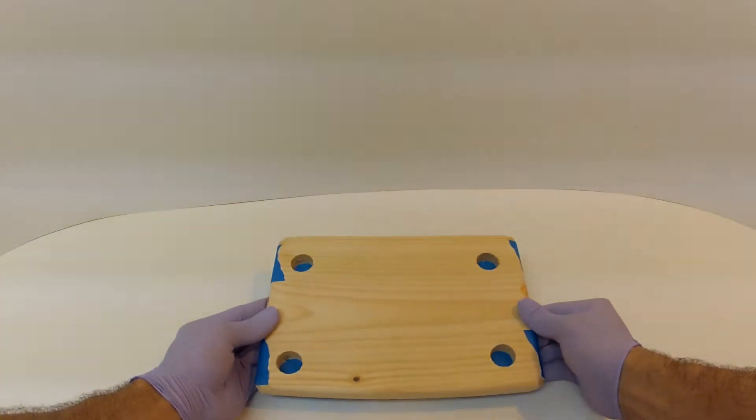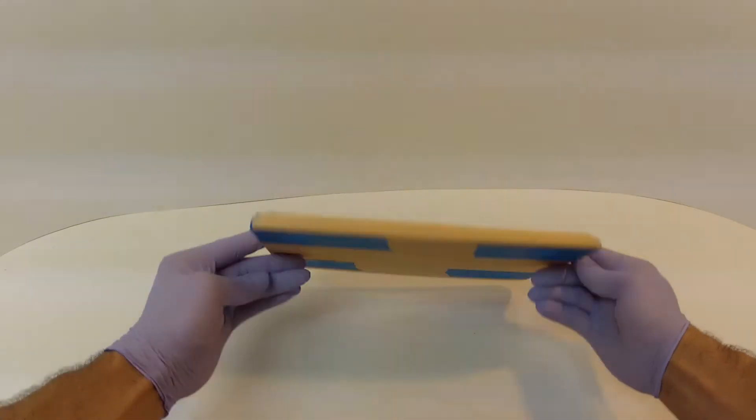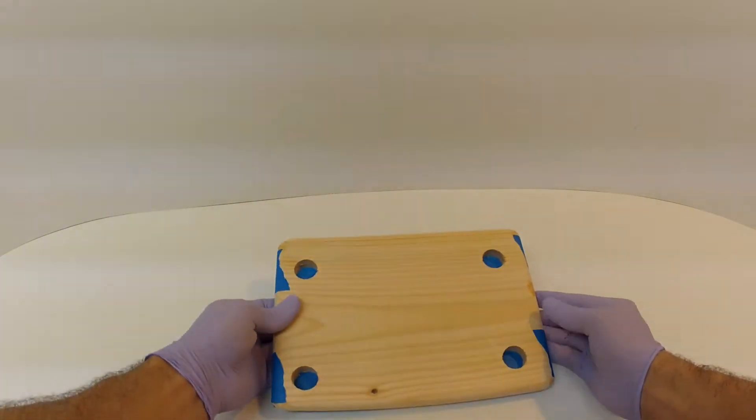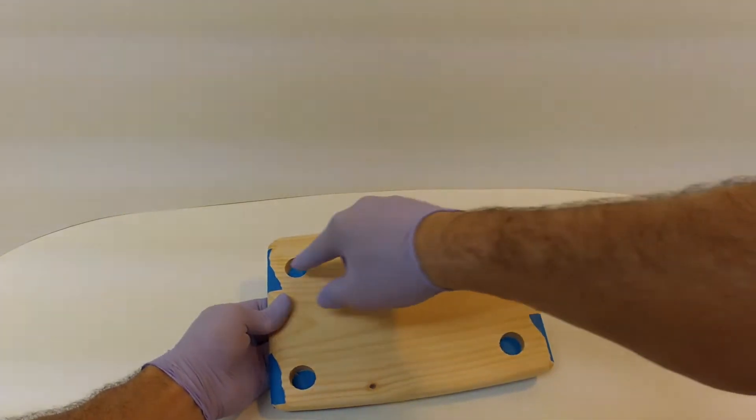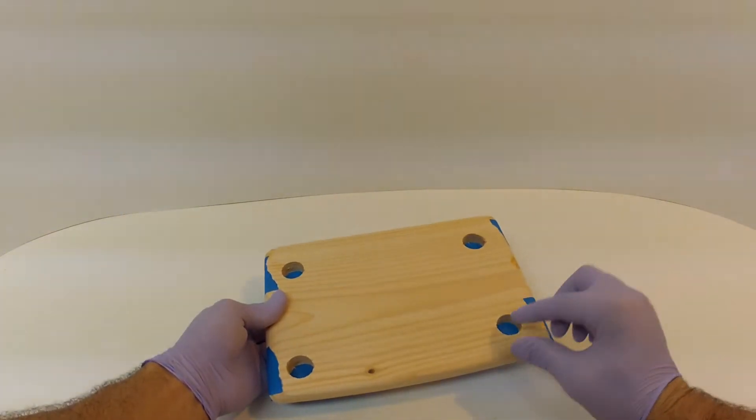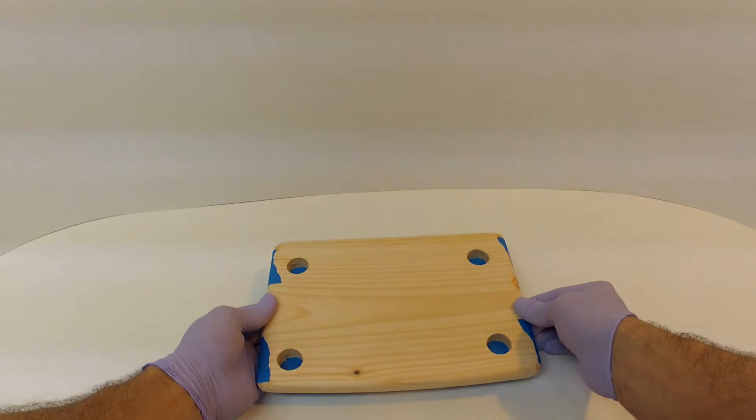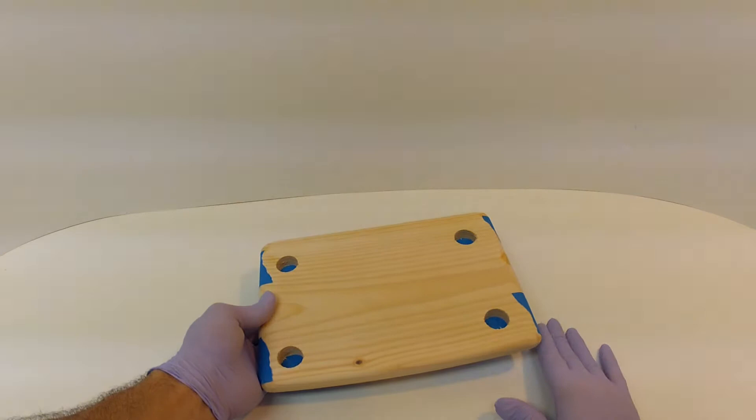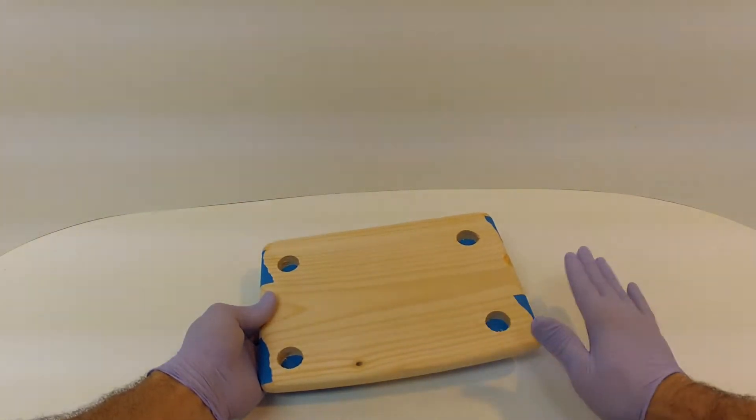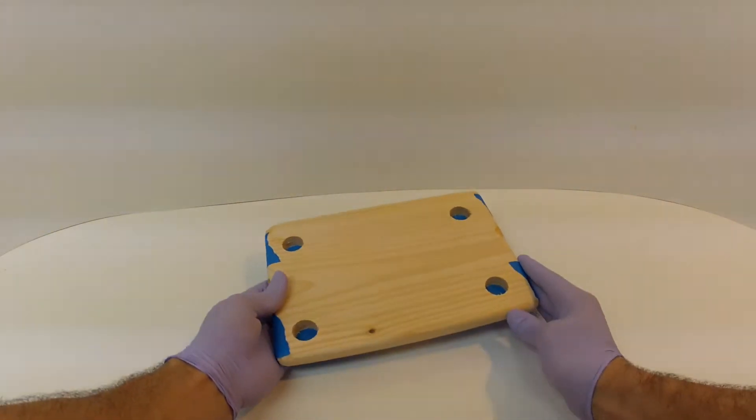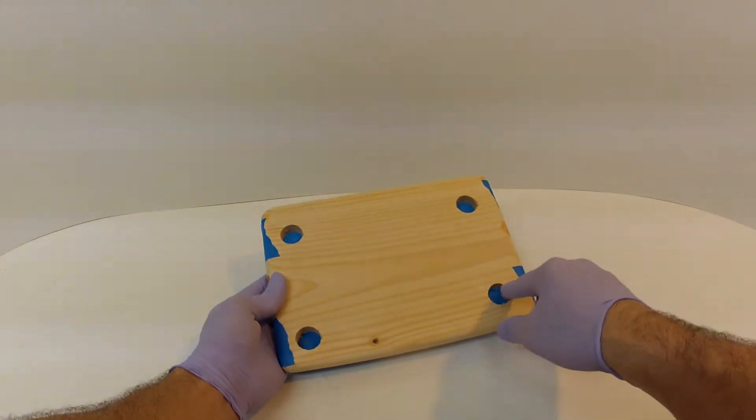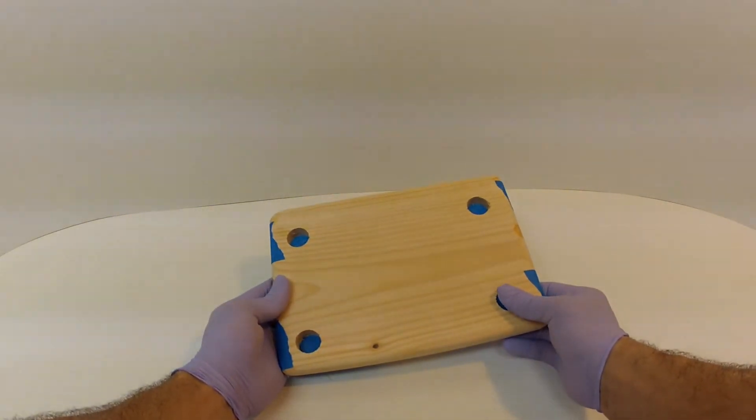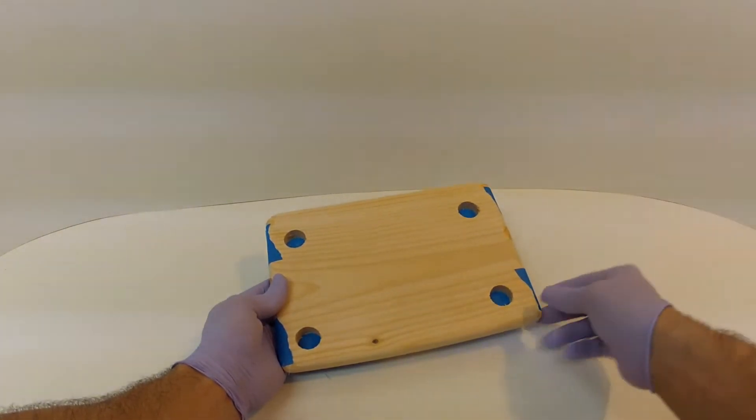Find out the spacing you are going to want to mount on your board and pre-drill like this, because we are going to fill this in with epoxy first. The reason for doing that is you fill this in with epoxy that cures, then you glass this part over, and then you take a smaller drill bit the size of the bolt.